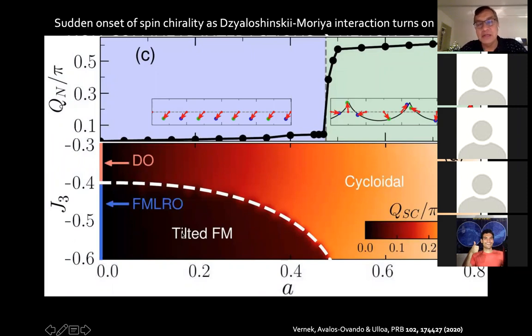and characterize that you can be in this tilted ferromagnetic phase like I showed you. If it is a small value, as I mentioned, there is this low tilting, but beyond a certain value that depends on other parameters, you can have a drastic jump. What this is illustrating is a sudden transition. This characteristic wavelength of the cycloid is essentially zero, and then all of a sudden it jumps. It's slowly, and all of a sudden, plop, it decides to make loops, if you will.